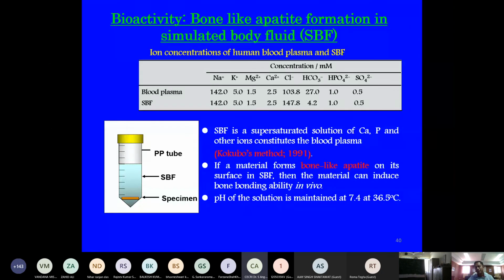Once we modify the surface, we do an in vitro study to evaluate the bioactivity of the surface. We take a blood plasma concentration in the laboratory by adding salts to ultra pure water or distilled water, and we make the simulated body fluid. There is a concept that if you soak the surface modified sample in the simulated body fluid and it forms calcium phosphate or apatite deposition on the surface, then we can say that the surface is bioactive.